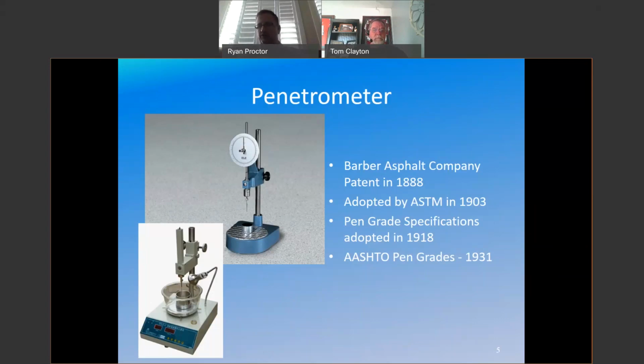And in the old days, they could store that asphalt at a variety of different temperatures. And you dropped the needle, which was a modified sewing needle, into the pin tin, and you measured how deep of a deflection you could get when the needle was dropped into the pin tin. There's also a weight, and the apparatus itself had weight. And for the most part, you dropped it for about 5 seconds, but again, there are varying specifications.